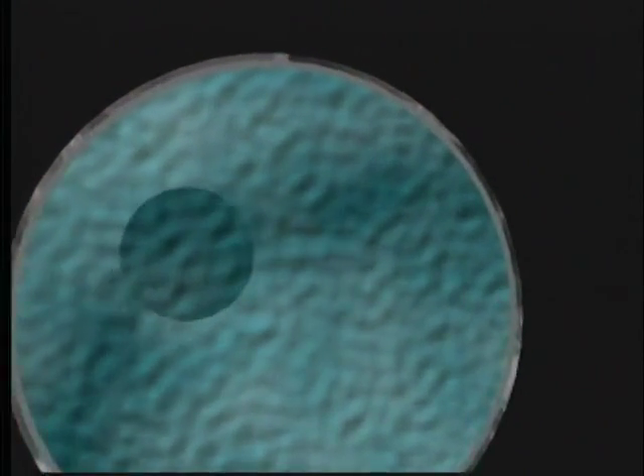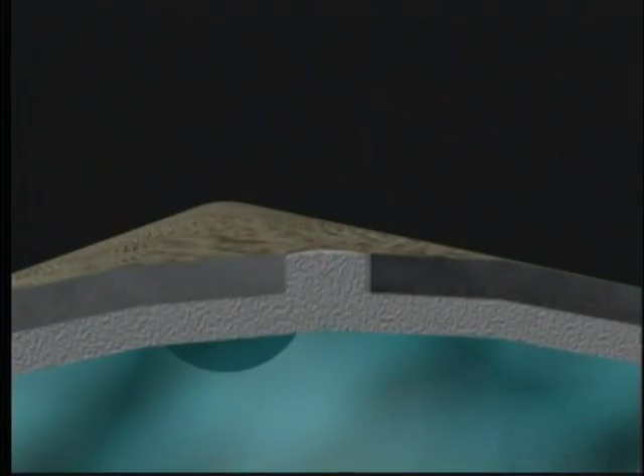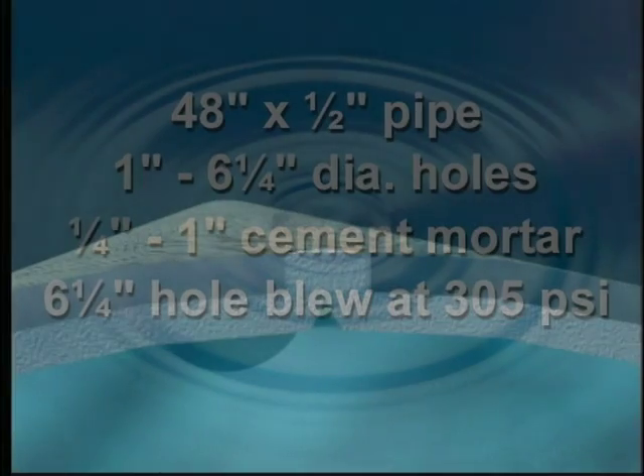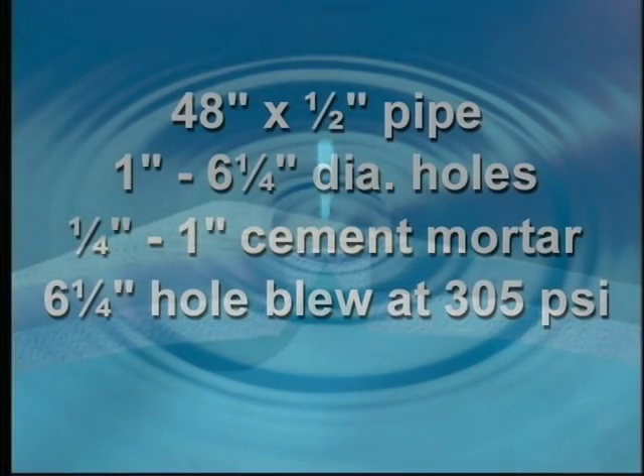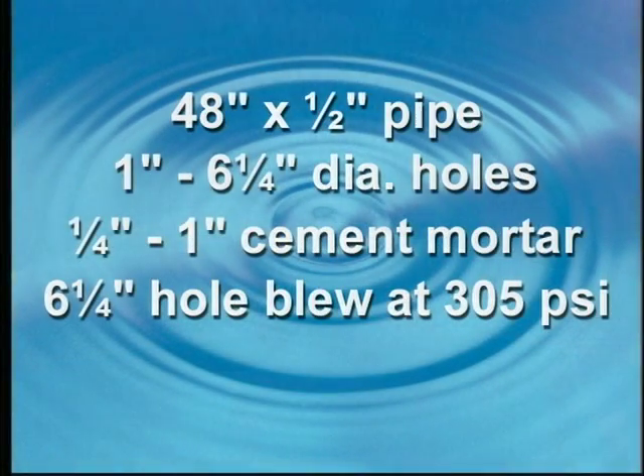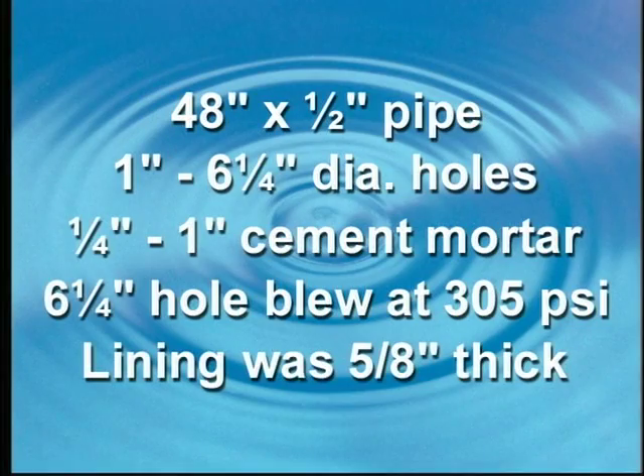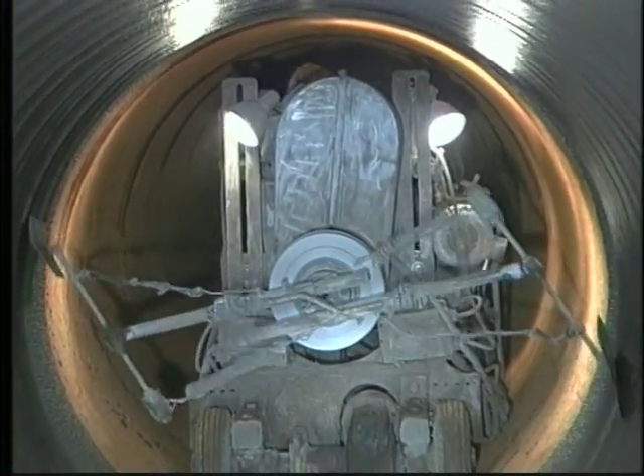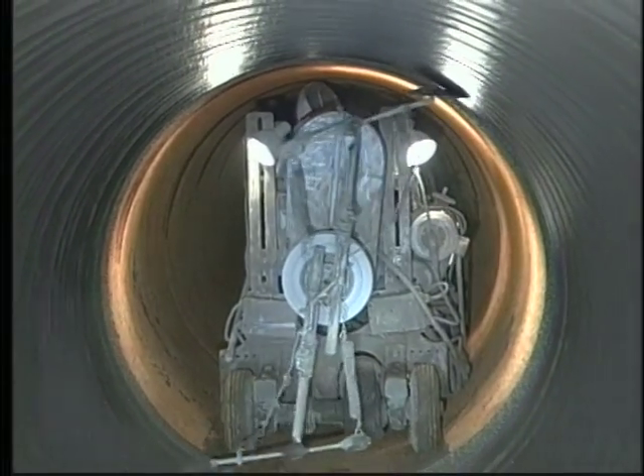A large hole, 6 1/4 inches in diameter, blew out at a pressure of 305 psi. The thickness of the lining at this particular hole was 5/8 inches. From this test, it is concluded that cement mortar lining, properly applied, provides positive protection against leakage under normal operating pressures.